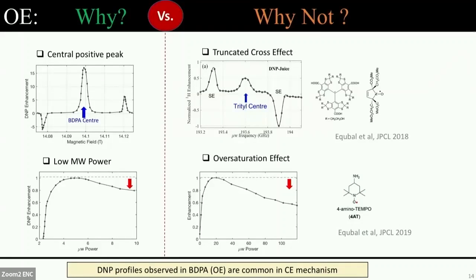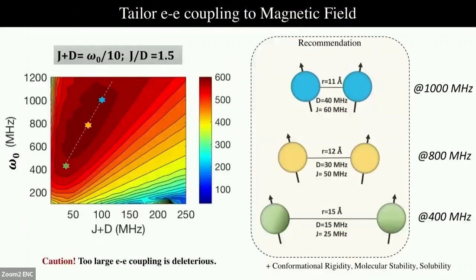Yeah, George. Yes, nice talk. Just wanted to know, so you're giving a recommendation which is to increase the J coupling for efficient DNP at high magnetic fields, let's say around 1 gigahertz or so. But we've seen, for example, that it's really critical to the number of bonds between two nitroxides or just a BDPA and nitroxides. For example, if you have 2 bonds, could be too short, too strong coupling, 3 bonds, too weak coupling. So, what modifications would you suggest in terms of synthesis to achieve that?